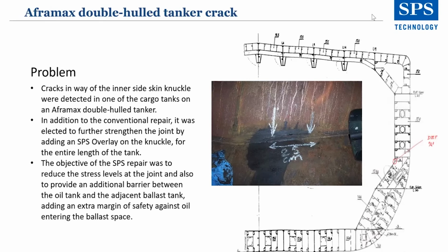The second case that I brought to attention is the Aframax double hull tanker crack. This crack was in the inner side skin knuckle in one of the cargo tanks on the Aframax tanker. In addition to a conventional repair, SPS was added on top over the knuckle for the entire length of the tank. The objective of the SPS was to reduce stress levels at the joint and also to provide an additional barrier between the oil tank and the adjacent ballast tank, adding an extra margin of safety against oil entering the ballast tank.